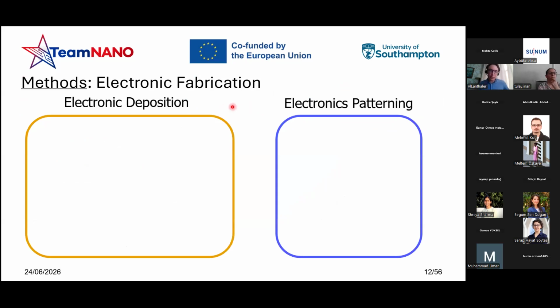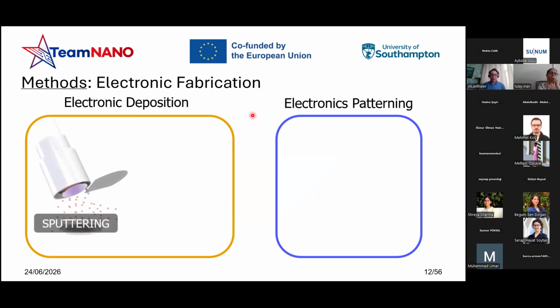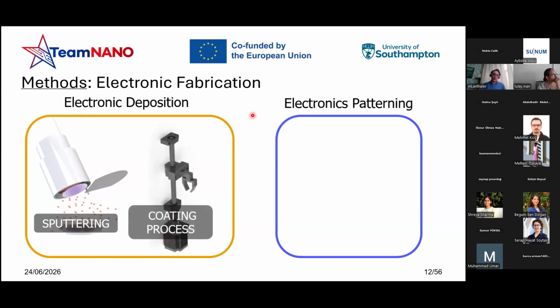Coming to the electronic fabrication, in my speech, the focus was mainly on the utilization of the sputtering technique. So basically, through the activation of a plasma on a metal, semiconductor or dielectric target, the idea is to detach atoms from the very target and deposit them through the activated plasma in a high vacuum chamber onto the very substrate of our interest, in our case, the textile. And the dip coating process. So the idea is to take advantage of the porosity of the textiles themselves, either yarn-wise or lattice-wise, to be coated with different materials.